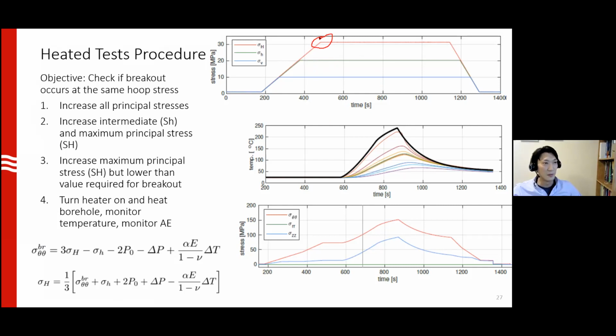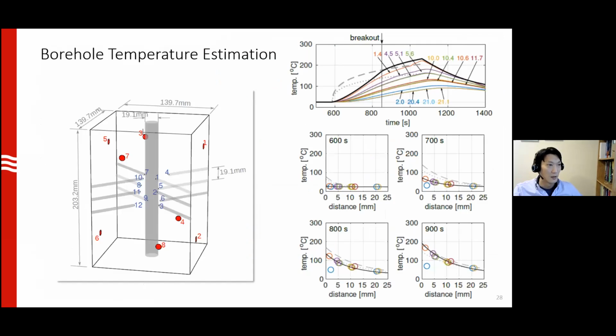So after we keep the maximum horizontal stress at a constant level, now we start heating the borehole, and this is the temperature data registered by the thermocouples we have. How do we use the thermocouple data? If we plot the temperature profile as a function of distance, so each of these thermocouples are at a different distance from the borehole, so you can get a temperature profile as a function of radius. And with the exception of this one sensor, it follows a quite nice trend. So we have models to fit this data, and that way we can extrapolate and understand what the borehole temperature is.